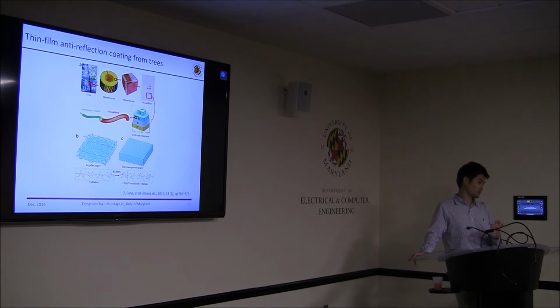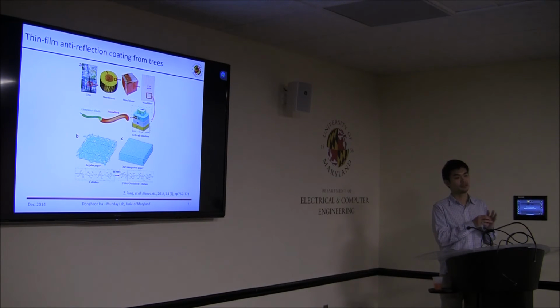The other thing we have to consider is that we want to use a pretty simple paper, and it shouldn't be thinner than 40 microns, because the fiber thickness is 40 microns. But if there are double layers or triple layers of the fibers, it is going to be thicker, so we don't want to do that. So the first thing is we need to keep the proper concentration, and the drying process uses some special techniques, like heaters and some kind of rollers. If we do the whole thing, we can make a single layer of the cellulose fibers. Yeah.